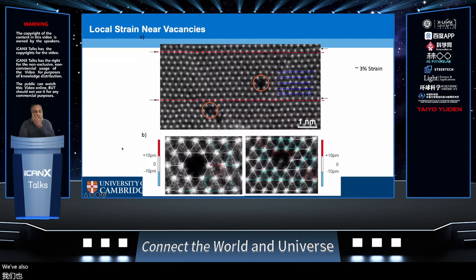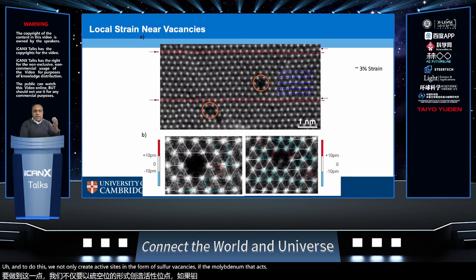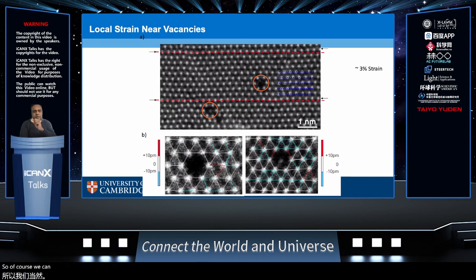We've also aimed to study step three, which is the thermodynamics of the catalytic activity. We want to get to a point where the delta G for hydrogen, the proton adsorption and hydrogen desorption, is close to zero. And to do this, we not only create active sites in the form of sulfur vacancies, it's the molybdenum that acts as the active site. So of course, we can access the molybdenum in the MoS2 quite easily by introducing sulfur vacancies.